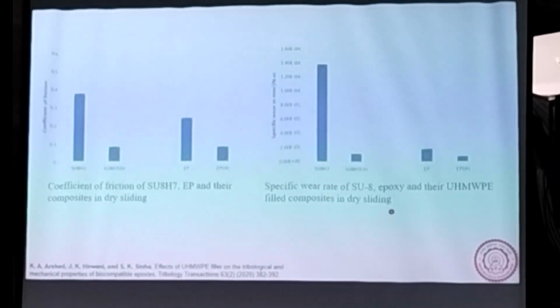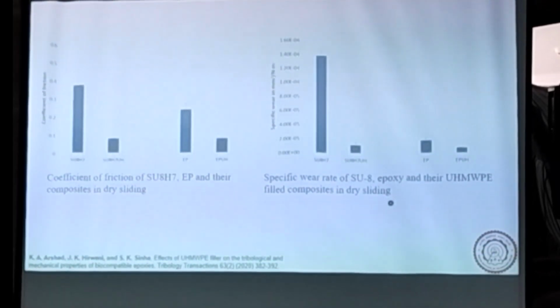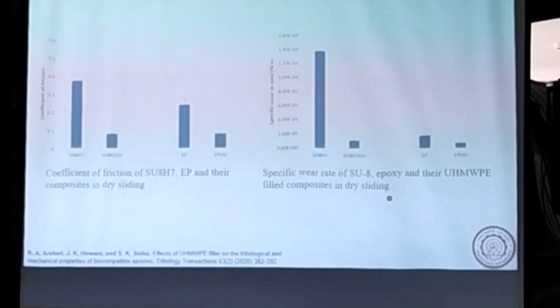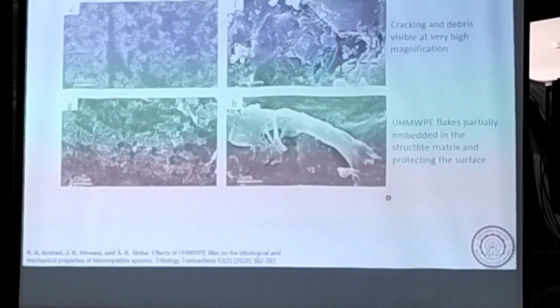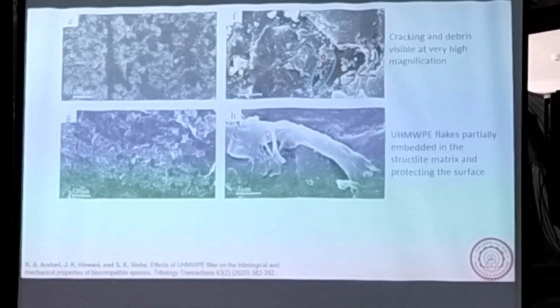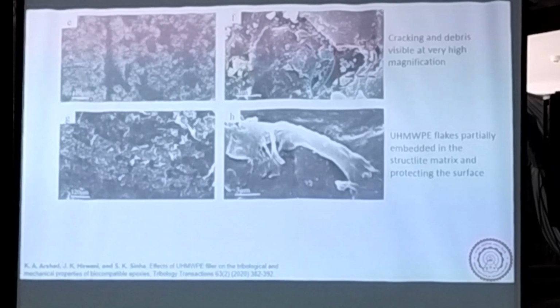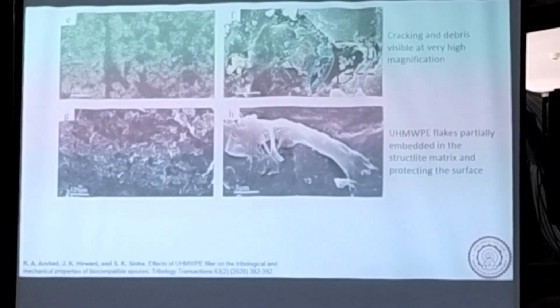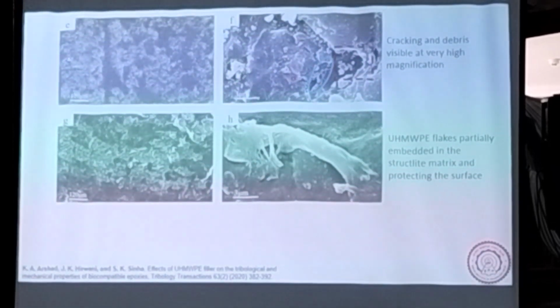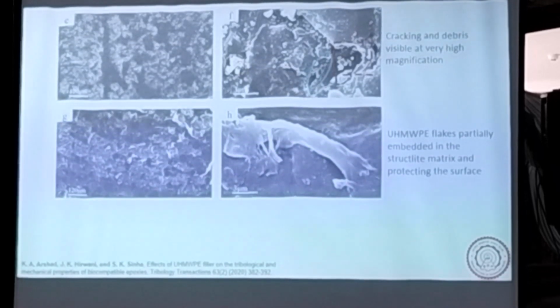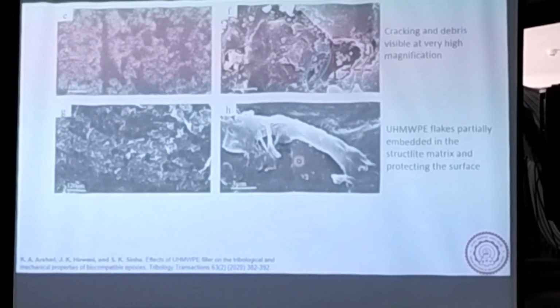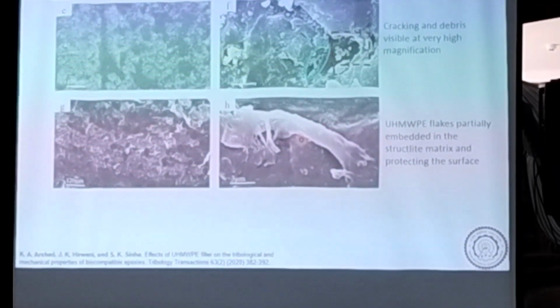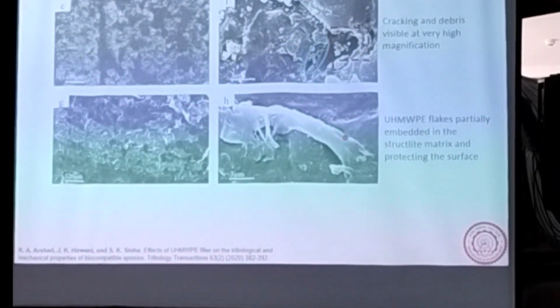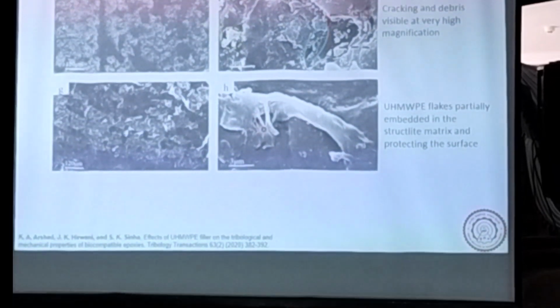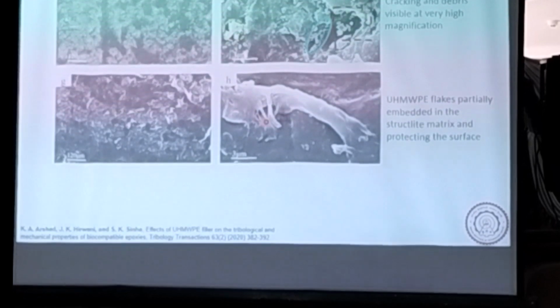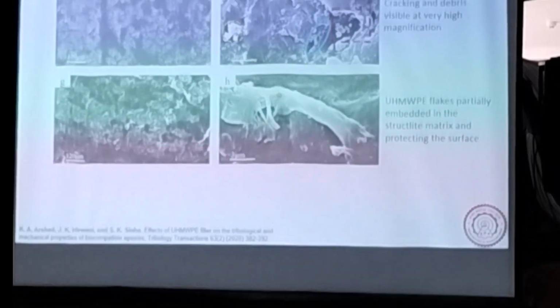But these are all dry tests. For hip joint application, we always conduct in lubricated sliding. So in the dry test, we saw that although the bonding is very good, we can find some places where there is crack initiation. So these are SEM pictures, and we can see that there are some UHMWPE flakes or particles attached to the matrix, which is sort of covering the surface here.